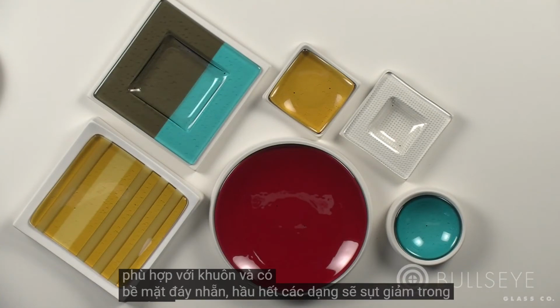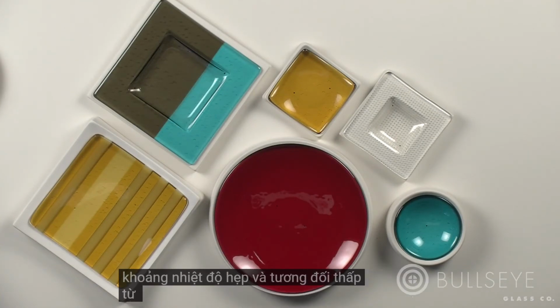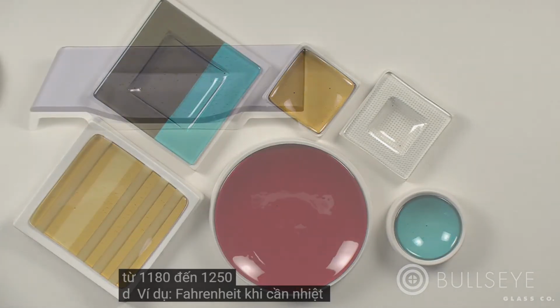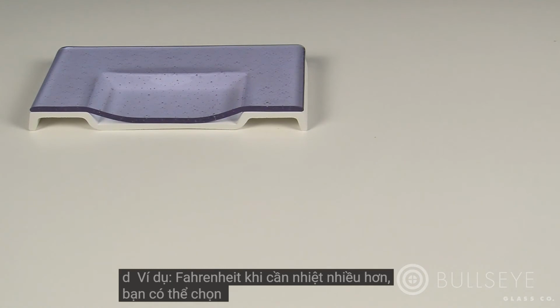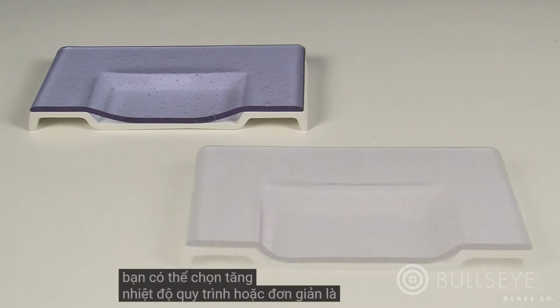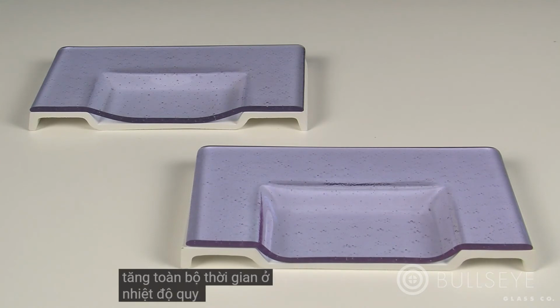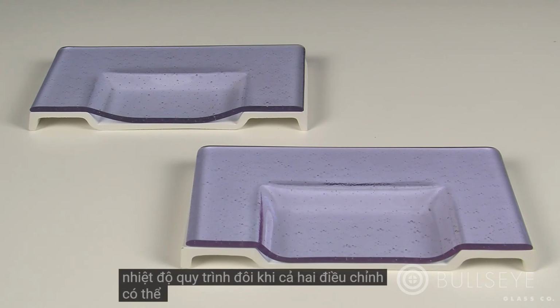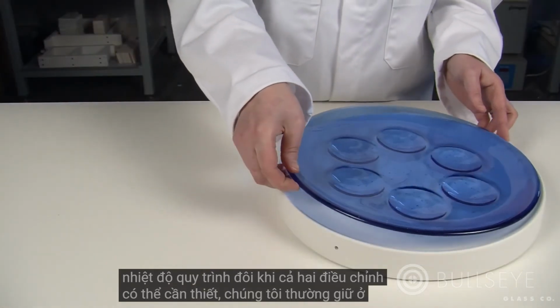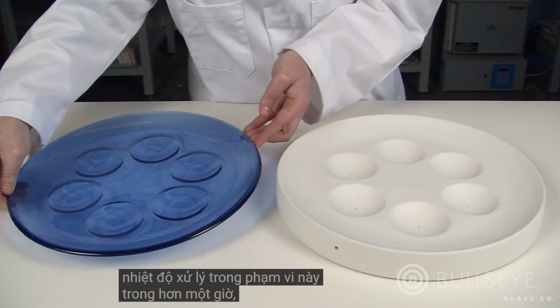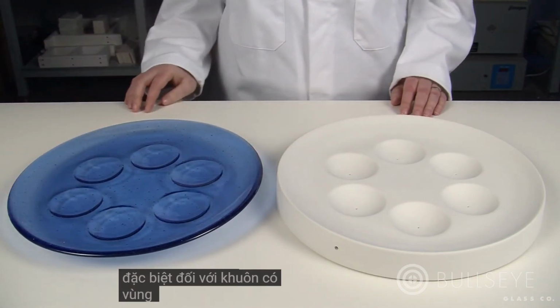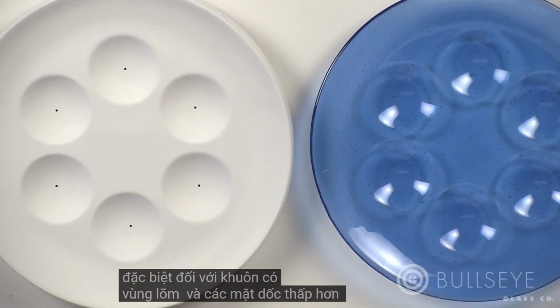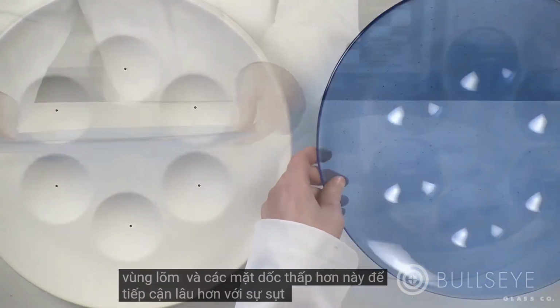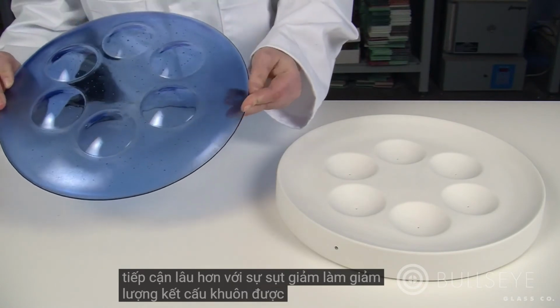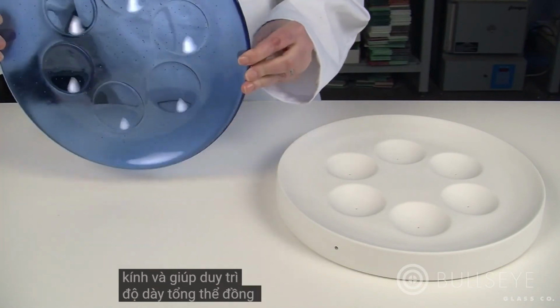Most forms will slump in the narrow and relatively low temperature range of 1180 to 1250 degrees Fahrenheit. When more heat work is necessary, you may choose to increase the process temperature or simply increase the hold time at process temperature. Sometimes both adjustments may be necessary. We commonly hold at process temperatures within this range for over an hour, especially for molds with recessed areas and steep sides. This lower for longer approach to slumping reduces the amount of mold texture picked up by the glass and helps maintain a uniform overall thickness.